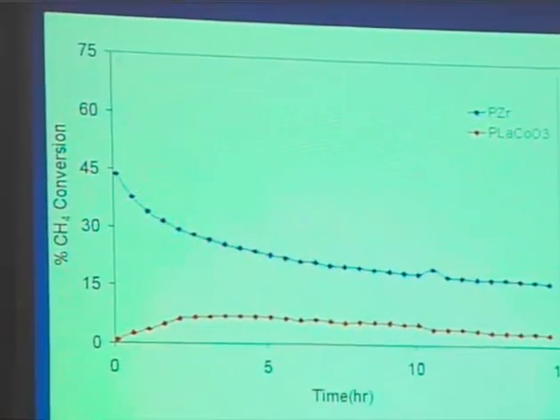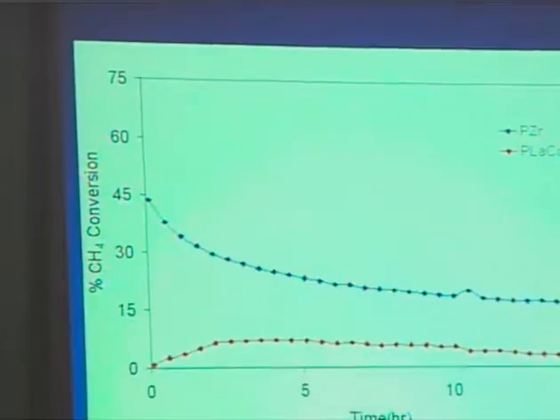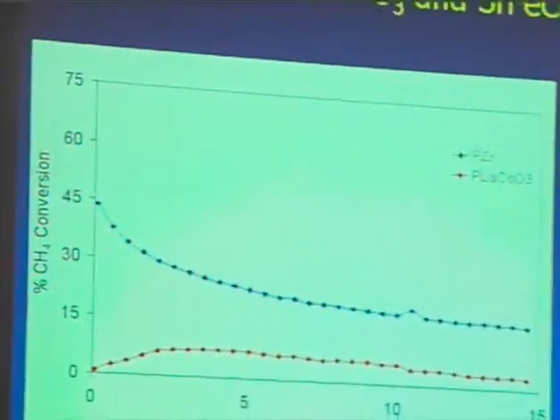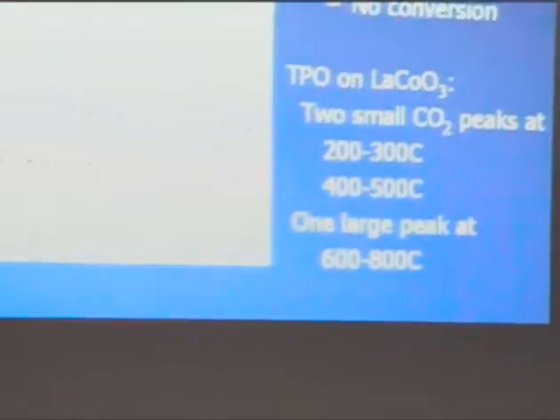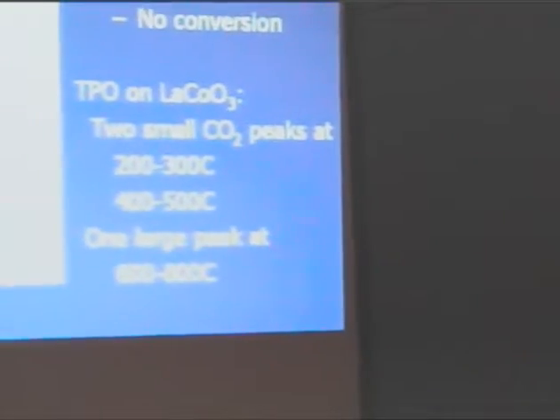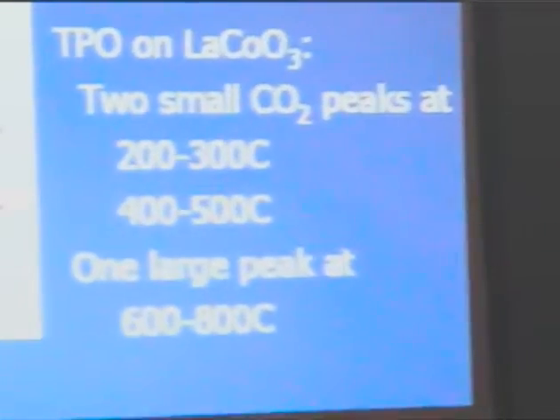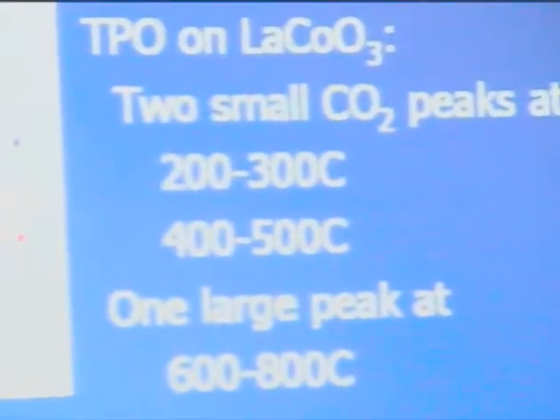When we did temperature programmed oxidation after reaction on the perovskite material, we saw 2 small CO2 peaks at lower temperatures and a very large CO2 peak formed at higher temperatures. So this deactivation is most likely due to carbon deposition on the material.